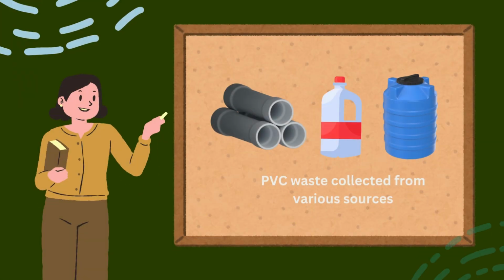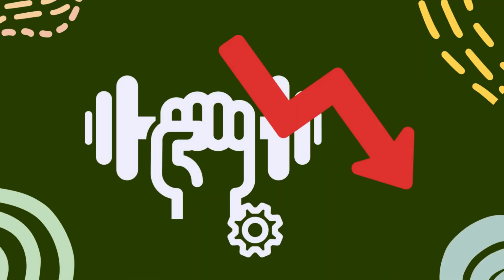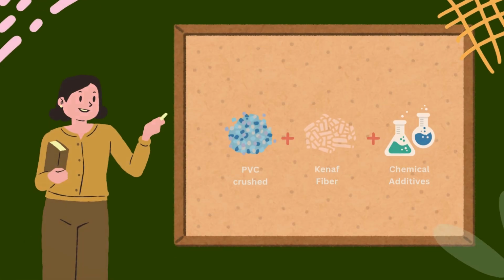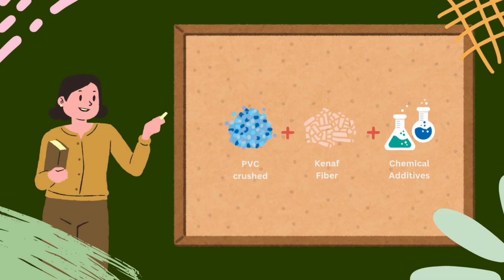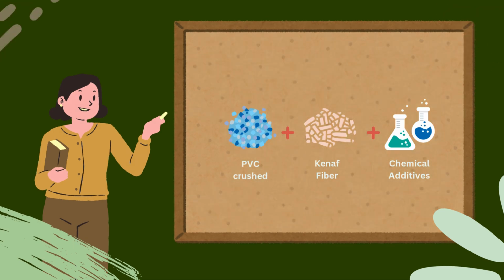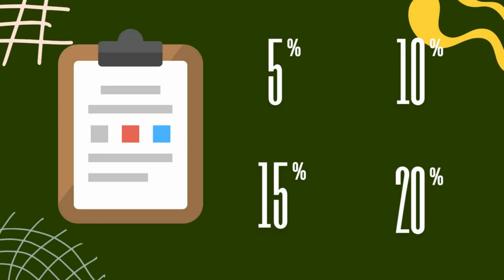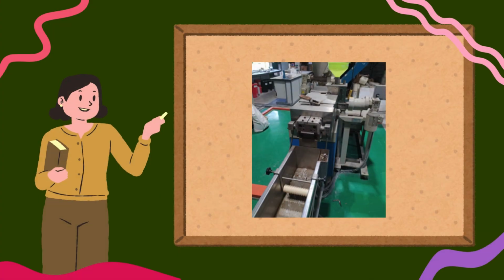Let's start with the basics. Our process begins with collecting PVC waste, which is then cleaned and crushed into small pieces. But recycled plastic, on its own, often lacks the mechanical strength needed. That's where our research comes in. We're focused on finding the best formulation to reinforce recycled PVC with Kenaf. Various parameters such as Kenaf loading of 5%, 10%, 15% and 20% have been considered, while formulation properties were used for furniture applications. To achieve this, we're using a twin screw extruder.